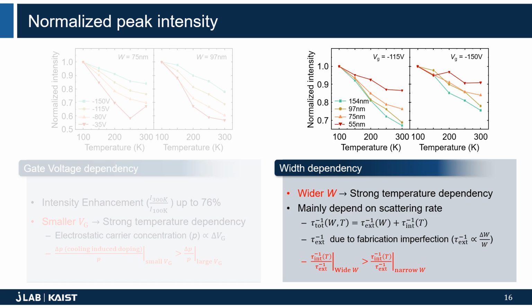There are intrinsic and extrinsic factors that affect the damping of the plasmonic response of graphene resonators. Such as impurities and dielectric phonons, intrinsic losses are introduced to explain how graphene plasmon depends on temperature. However, extrinsic losses, which are induced by geometrical irregularity, are independent of the temperature. Fabrication imperfections like edge effect or proximity effect hence produce irregular unit cell periodicities. These fabrication constraints impact the broadening of the resonance, whereas the intrinsic losses are mainly temperature-dependent factors.